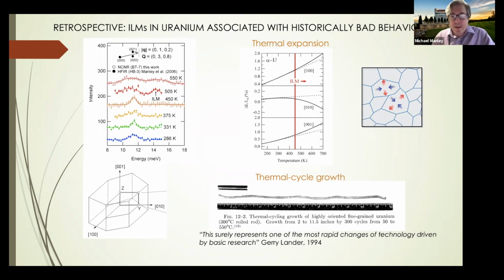So anytime you thermally cycle uranium over a wide temperature range, it will tweak itself a little bit. I mean, this is a dramatic example, but it will always tweak itself a little bit because the internal strains are large enough to go plastic, and so they don't completely recover. And so it builds up over time.